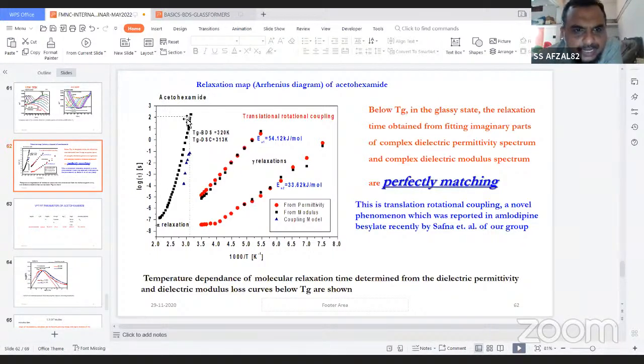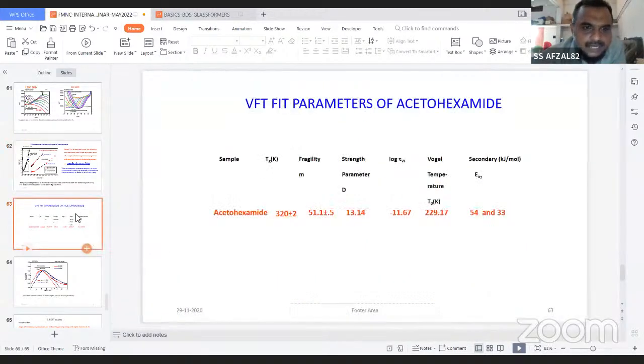Moreover, you can see in the supercooled liquid state, that is above the glassy state, the alpha relaxation is shown non-Arrhenius, that means non-linear temperature dependence, which corresponds to the non-Debye process. That is, a normal Debye relaxation versus non-Debye relaxation. And finally, we fitted this with the VFT equation, which is normally used for fitting the Arrhenius plot of the alpha relaxation. And we got the parameters. These parameters are very crucial for understanding the stability of the glassy state.